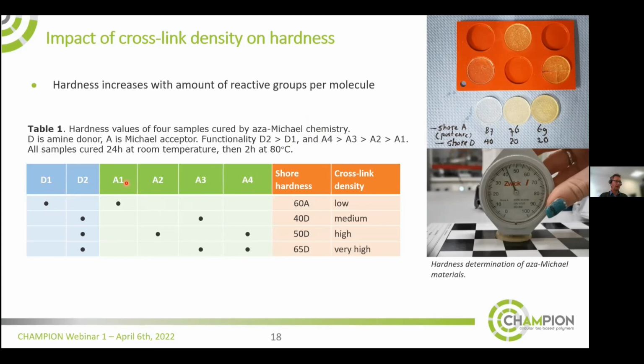And here you see 4 different Michael accepting pre-polymers, in which again, functionality of A4 is larger than A3, which is larger than A2, which is larger than A1. And if you use combinations of diamines and Michael accepting pre-polymers that have a relatively low functionality, functional density, then you end up with relatively low values for the shore hardness. And in this case, you also have quite a low cross-link density. But if you go to more functionalized materials, you see that hardness increases, and this corresponds to the cross-link density of your polymer network. Shore D hardness is a very convenient hardness type because there are easy tools to use to measure hardness. So you can be very quick in your screening of materials.